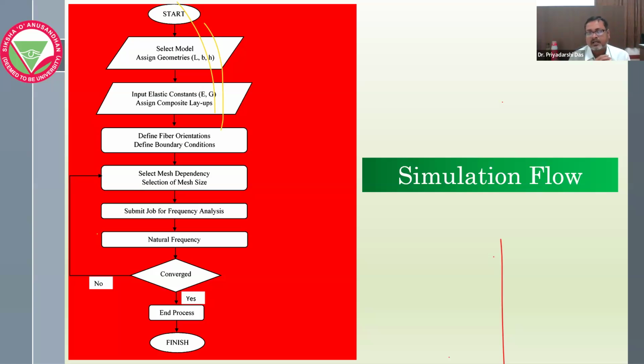In my research, I have taken the bidirectional fiber, that is quasi-isotropic. Quasi-isotropic means the material is composite, but it behaves like an isotropic material. So E is constant: whatever E I have taken, E1, E2, E3 in all 3 directions are the same. Then G1, G2, G3 are all the same. So in our research, E and G both are the same. If E and G are the same, it behaves like an isotropic material, but actually the material is composite. This is called quasi-isotropic material.